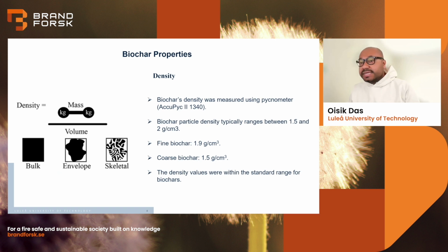So before we start adding biochar to concrete, we have to understand what the properties of biochar are and how these properties will affect the concrete. The first thing we need to understand is the density. We have calculated the biochar's true density using an instrument called a pycnometer. Usually the density ranges between 1.5 to 2 gram per centimeter cube. In our case, the fine biochar, which was made from wood, had a density of almost 2 gram per centimeter cube. And for the coarse biochar, the density was 1.5 gram per centimeter cube. So the density we have calculated is within the standard range for biochars.